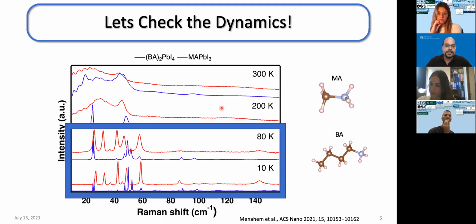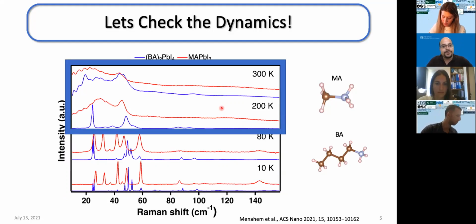Of course, there are changes because it's not the same material. And we also see that the spectra are well behaved. Every peak is a Lorentz oscillator, a Lorentzian shape. They blue shift and sharpen as we go down in temperature, which tells us that their structural dynamics are very, very similar. Again, it makes sense because of their related structures and because they both have orthorhombic symmetry at this temperature range.